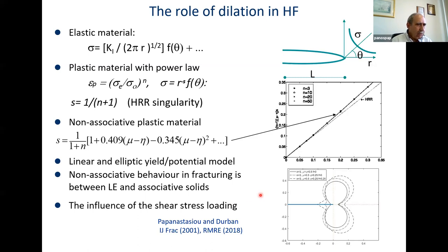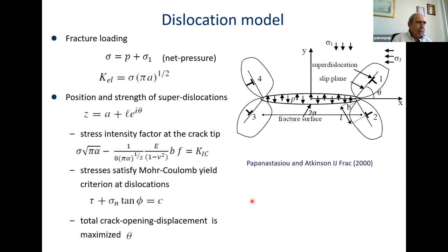One of the things we found with non-associativity is that it gives a kind of a boundary layer in the stress concentration near the fracture tip. And more recently, we did some calculation looking into the influence of the shear stress loading from the viscous fluid. And again, the difference it makes is in the emergence of these boundary layers in the stress concentration near the fracture tip. But I will not spoil it further. Let's go to more obvious things.